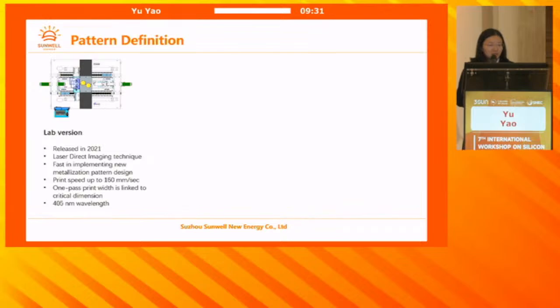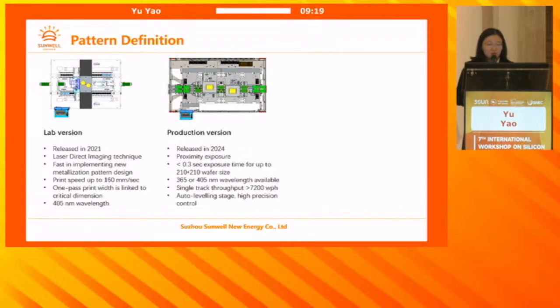But it's limited with a printing speed up to 160 millimeter a second. And it's using laser, so it's 405 nanometer wavelength. And this year we have a production machine with a proximity exposure method. We have the exposure time less than 0.3 seconds, and we have 2 wavelengths available from the LED light source. And now the single track machine has a throughput of more than 7,200 cells per hour.